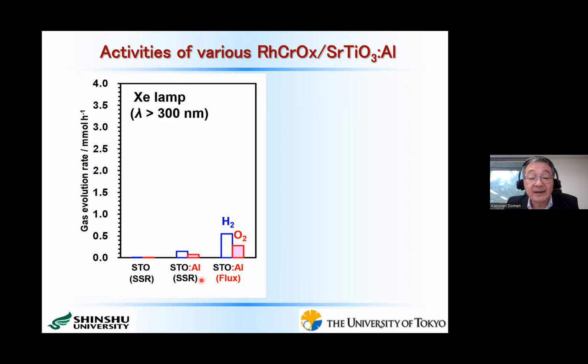But after aluminum doping by solid state reaction, obviously the activity is enhanced like this one. However, when we use the flux method, as I showed in the previous slide, obviously that activity enhancement is much better. And at this stage, the apparent quantum yield at 365 nanometer was 30%. This is already considerably good quantum efficiency at 365 nanometer, which is included in sunlight.